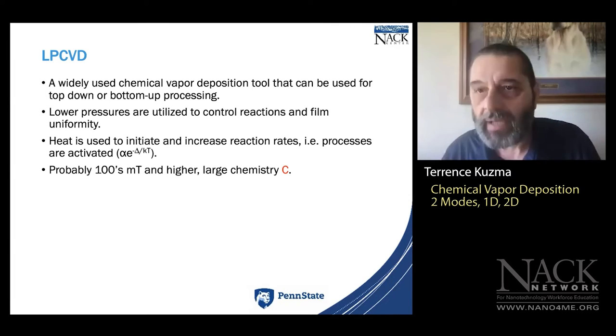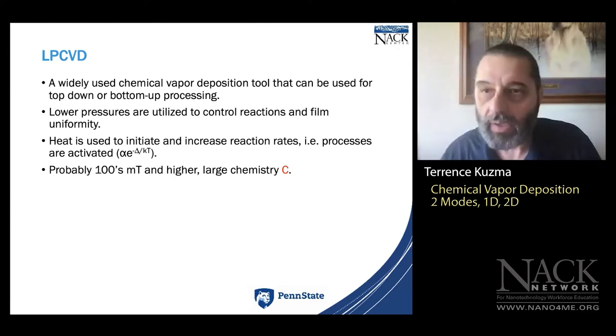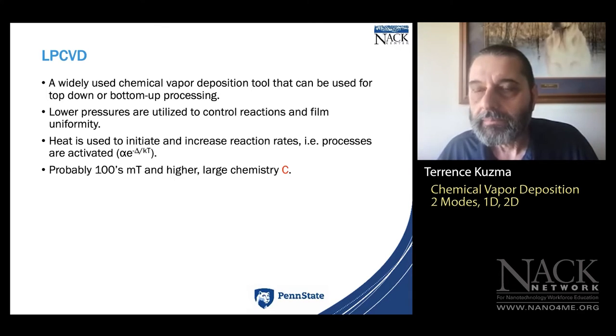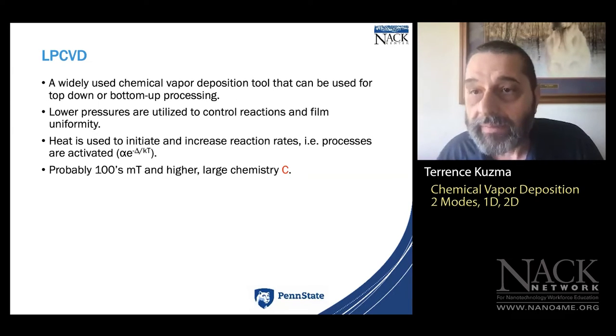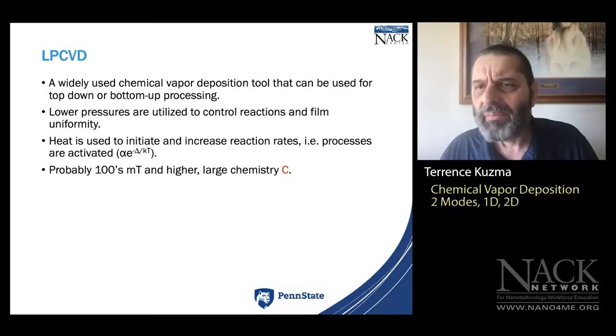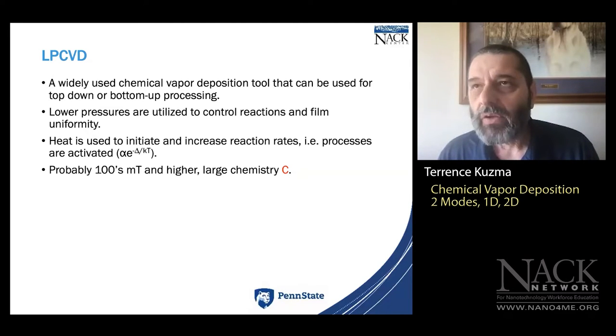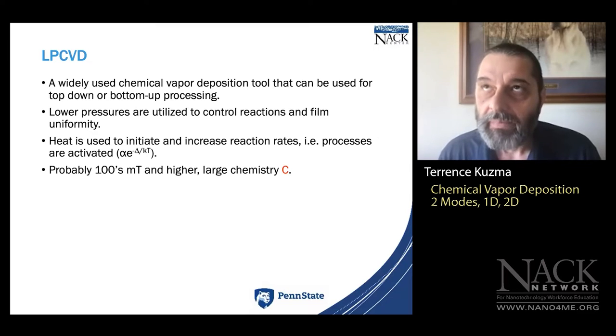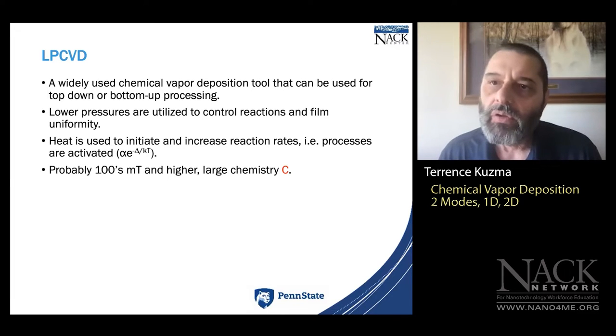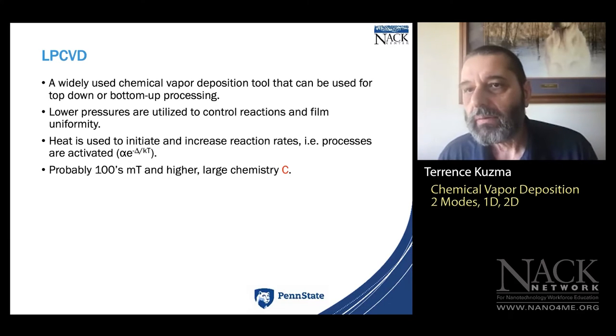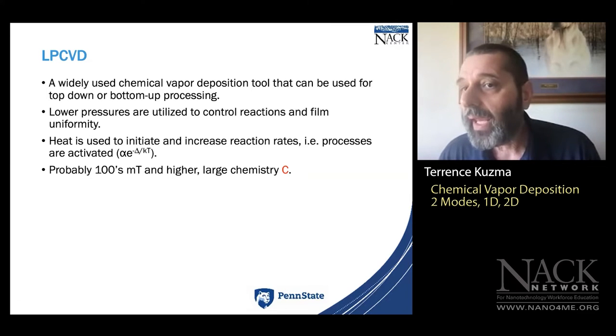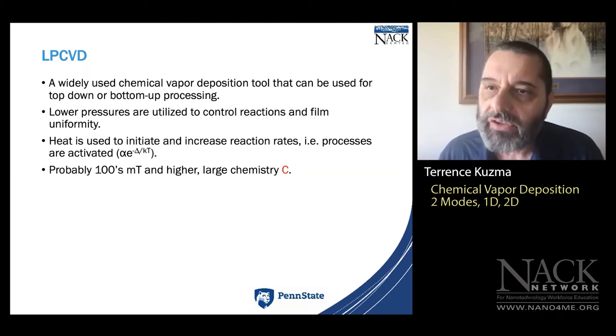Interestingly, the actual deposition time for a coating — like on sunglasses — is usually only minutes. But putting the material in the furnace and taking it out takes hours due to thermal stress management. So manufacturing time is not limited by deposition — it's dominated by the thermal ramp-up and cool-down.